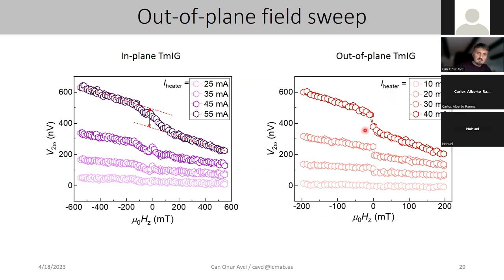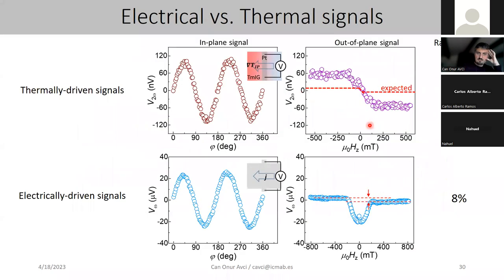So this is an out-of-plane magnetized garnet. And as you can see here, there's a very clear out-of-plane signal proportional to the Z component of the magnetization. That was not something we understood at that time because it was not explainable by existing phenomena.